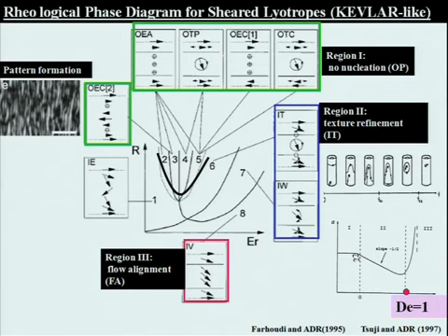Very low shear rate part, you have pattern formation. Then you have a parabola here, you have out of plane modes, and then outside this parabola, at high shear rate, you have back to in-plane modes with all kind of bifurcation cascades that were discussed in this meeting and previous meeting, I think in the liquid crystal meeting. The key point, you have pattern formation here, band formation.